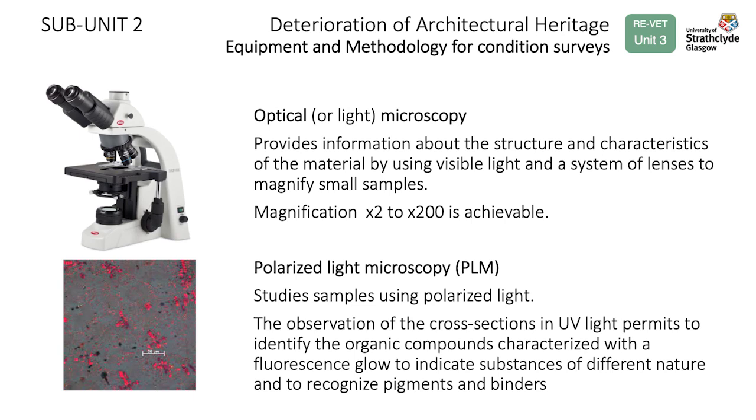Polarized light microscopy, PLM, studies samples using polarized light. The observation of the cross-section in UV light permits us to identify the organic compounds, characterized by a fluorescence glow, to indicate substances of different nature and to recognize pigments and binders.